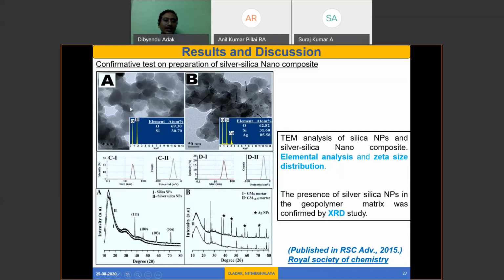A shows the image of the nanosilica, and B shows the silver-silica, and the black dots are the silver particles present in the silica nanocomposite. Also, from the EDS you can see the silver Ag peak. Similarly, this was confirmed with the zeta potential method and also with the XRD method, and we confirmed that the material is silver-silica. The preparation of the silver-silica nanomaterial is done.